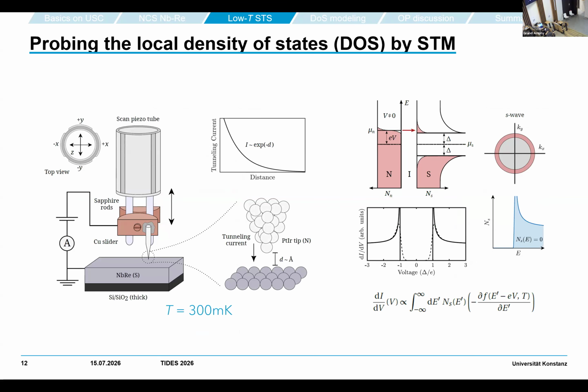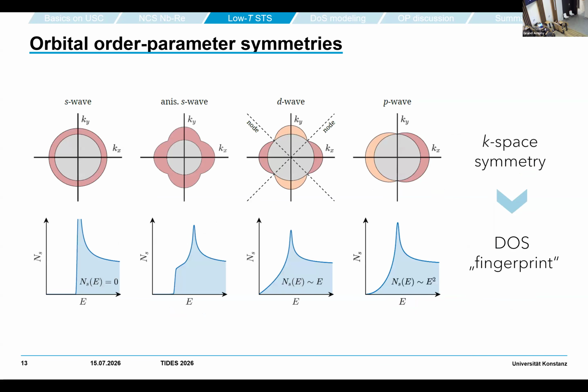This is the typical concept in STS for investigating superconductors, and the hope is that we find fingerprints of the K-space symmetry of the order parameter. When it's S-wave, we expect fully gapped spectra. When it's anisotropic S-wave, still S-wave but with modulation of the amplitude, we'd expect something still fully gapped but with modulation in the shape. When there are nodal lines, we will have in-gap states, and depending on the order parameter symmetry, D-wave or P-wave, the shape inside the gap would be different.